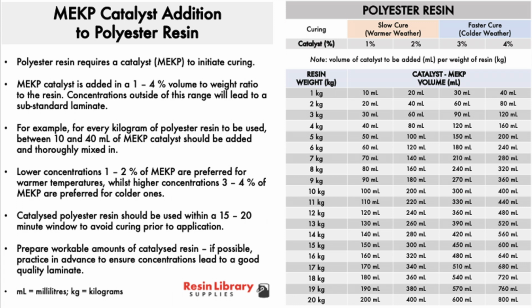Catalyzed polyester resin should be used within a 15 to 20 minute window to avoid curing prior to application. Prepare workable amounts of catalyzed resin. If possible, practice in advance to ensure concentrations lead to a good quality laminate. The table on the right shows the different quantities of resin in kilograms and the corresponding volumes of catalyst that would need to be added to hit specific concentrations.